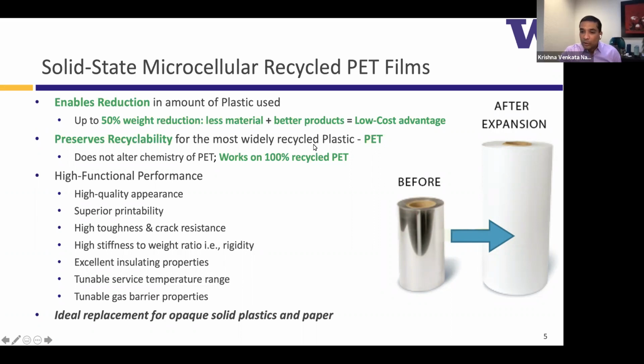And because the bubbles are so small, in many cases they're smaller than the critical crack propagation radius, you find that the material is unbreakable. I mean, you can continuously try to break it with your hand, it won't break. You'll find that because of the bubbles, the material is more insulating than what materials are out there. So this better performance with less material gives you a low cost advantage. And because we're only using CO2 gas, you can preserve the recyclability because the chemistry of the plastic is not changing in any way, right?